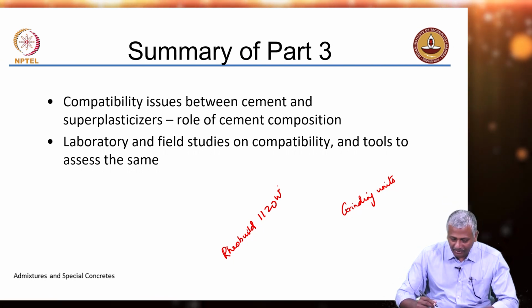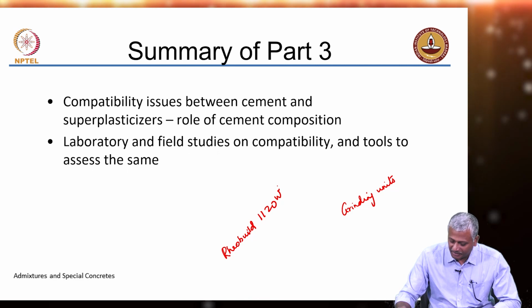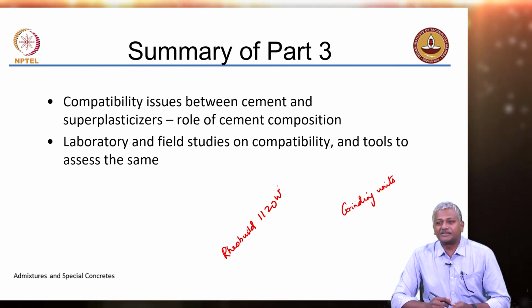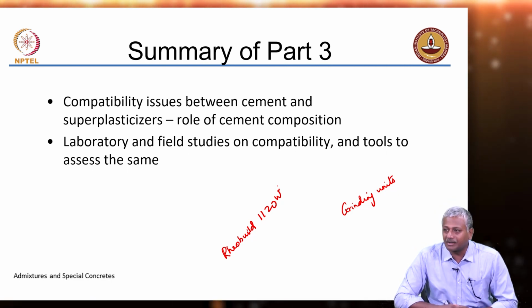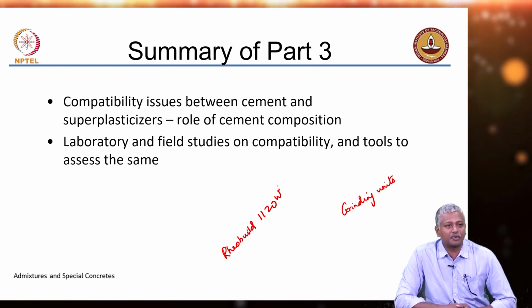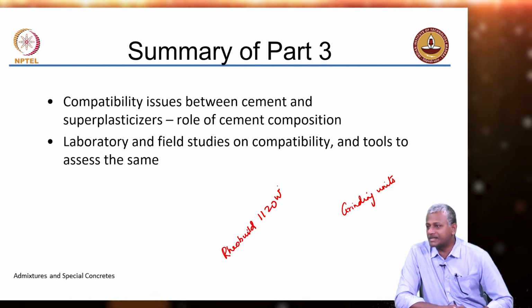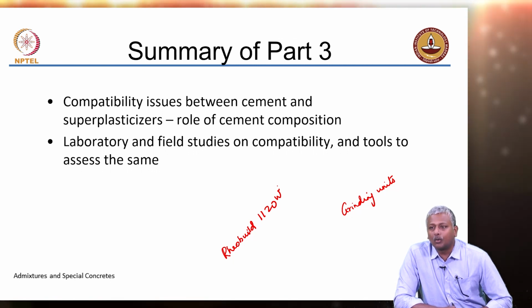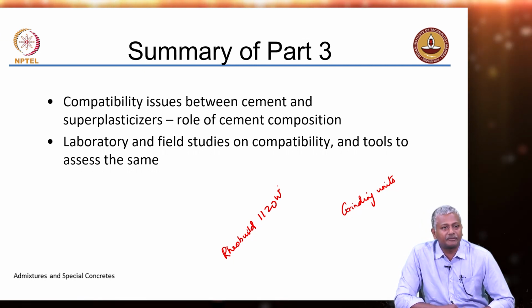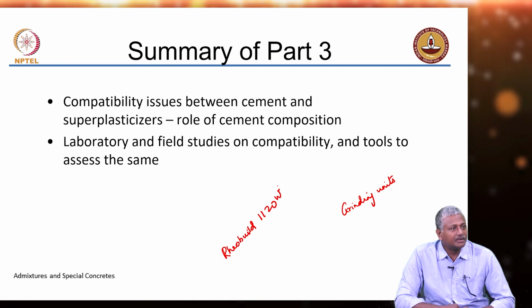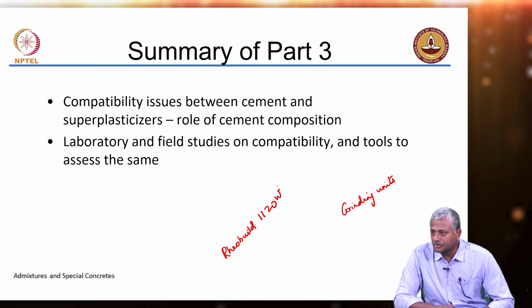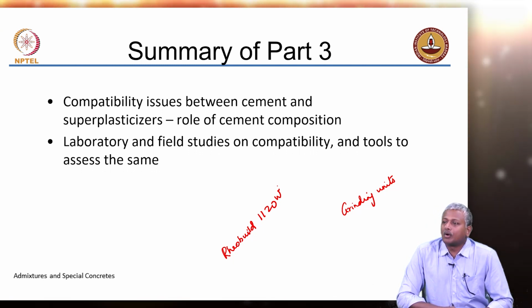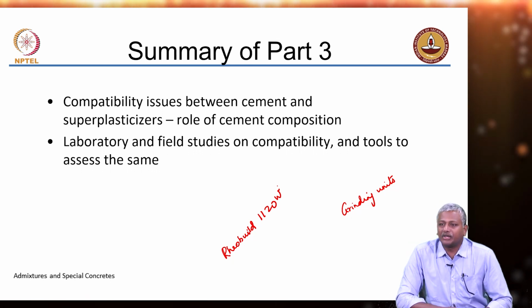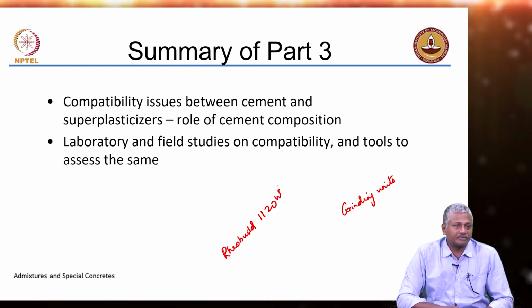So, again, just to give you one more example, it is not only all of these factors, there are other things also. For instance, there was a project where we were looking at designing concrete which had very low water content, about 130 kilograms per cubic meter. Of course, a PCE superplasticizer was used. Now, when you have a very low water content, I have already talked about the fact that you need to have an extremely good mixing process.